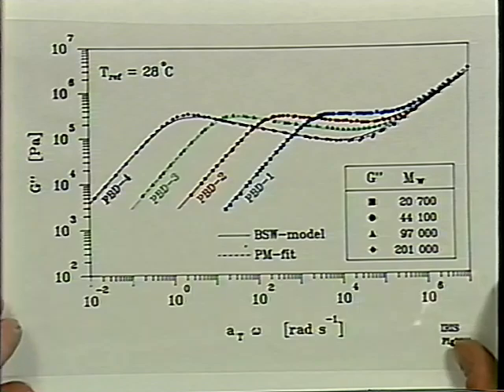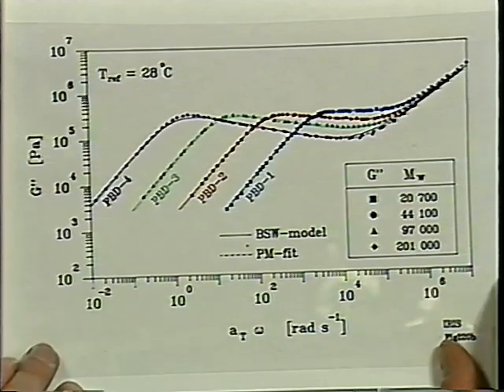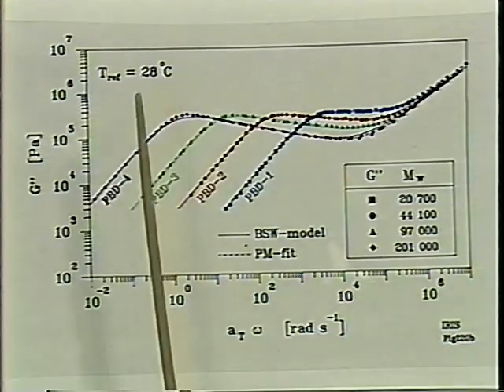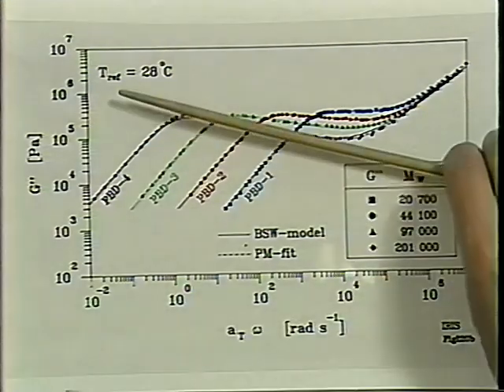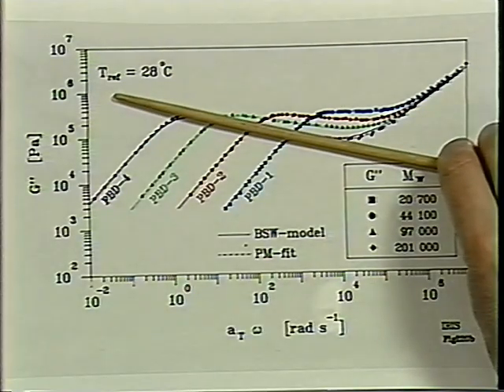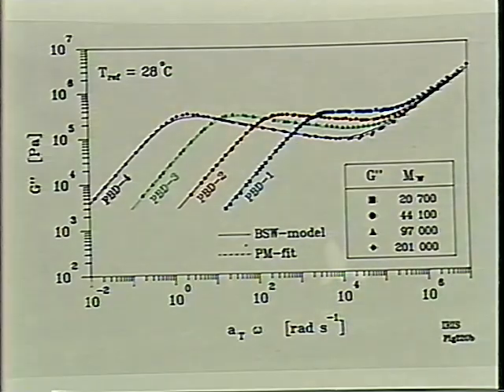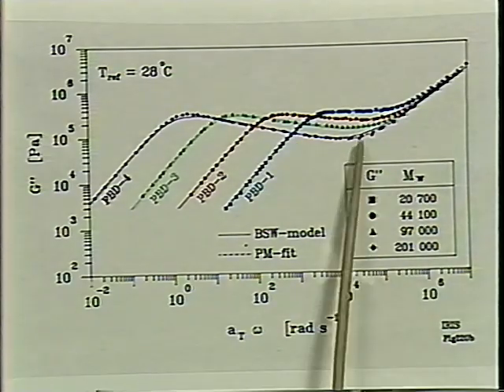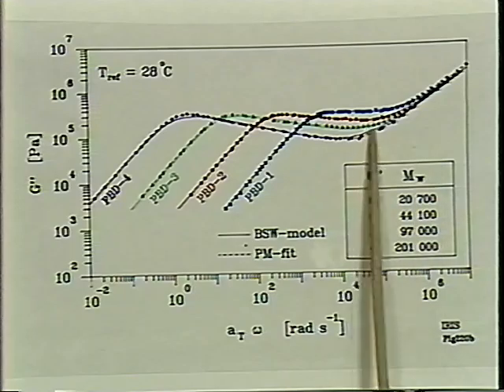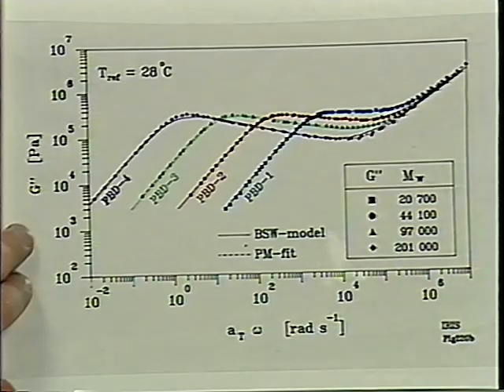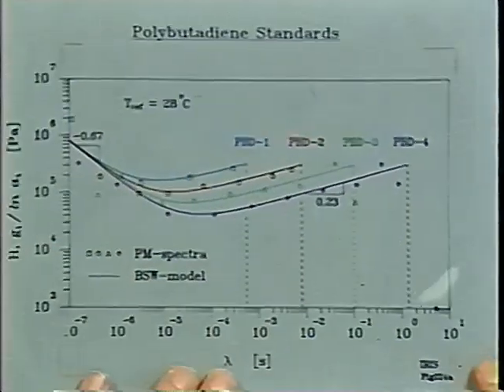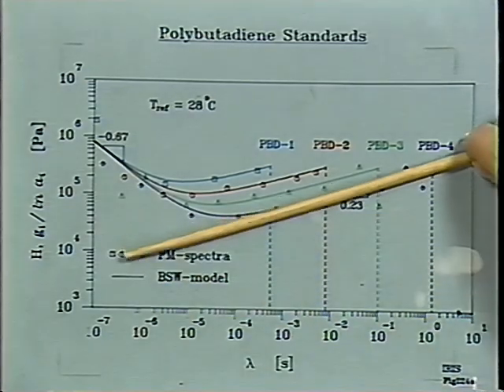Again, it's a very simple pattern we are looking at. We have a breakpoint in the spectrum. There's a linear region in the entanglement regime of the material. And then at short times, at high frequency, there is a transition to the glass. Now, this pattern has been analyzed, and the result was a simple self-similar behavior which consisted just of a straight line in a log-log plot.